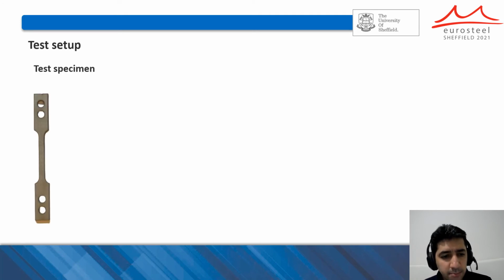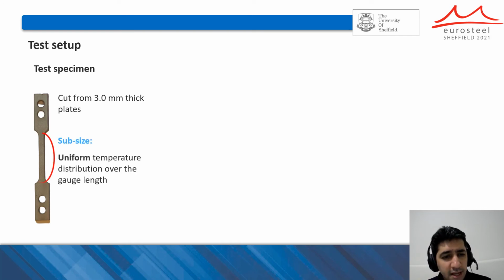As to the test setup, first the test specimen was cut from a 3 mm thick plate, and a subsize specimen was used because imposing a uniform temperature distribution over the gauge length of a subsize specimen is easier than for a larger specimen.